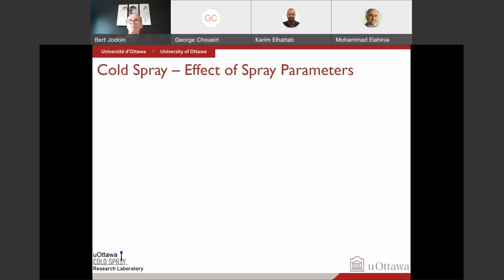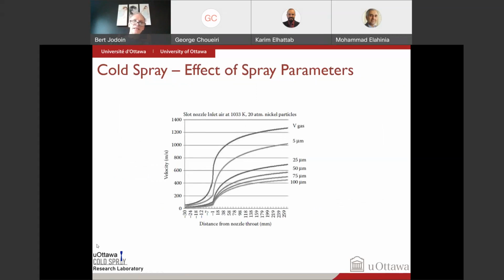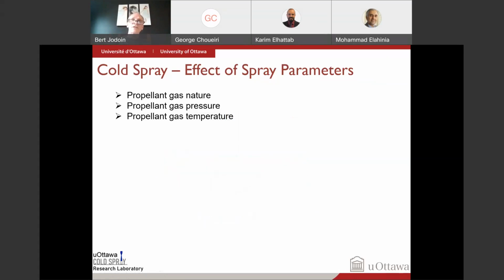The effect of the spray parameters now. Here you can see the velocity as a function of the distance inside the nozzle. So when you go in the nozzle, the gas accelerates to supersonic speed, and these are particles that you would inject depending on their size. So you can see obviously smaller particles will accelerate and get closer to the gas velocity. So that would tell you, okay, try to use small particles because they're going to accelerate a bit more, a bit faster. Effect of the propellant gas nature, gas temperature, gas pressure.